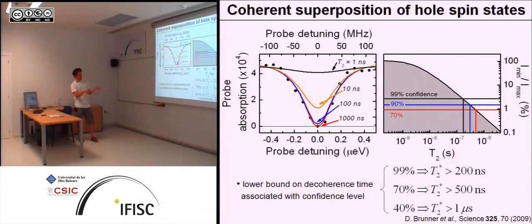So we can now say from our measurement results that the hole spin will be coherent for longer than 200 nanoseconds with a 99% certainty. And as you increase this number to half a microsecond, this goes down to 70%, but still with 40% certainty we can say it's 1 microsecond or longer, which is quite significant.